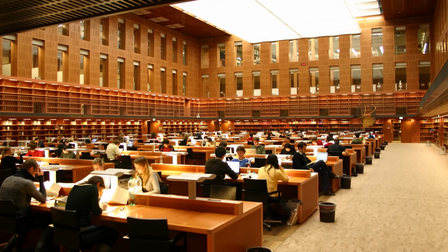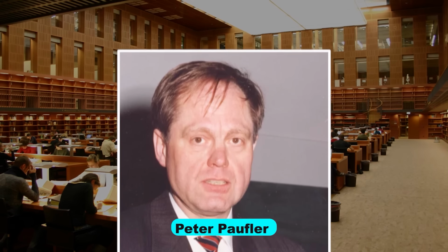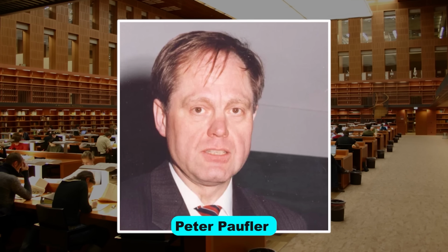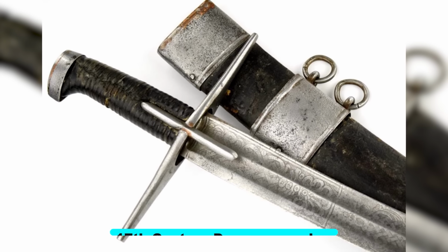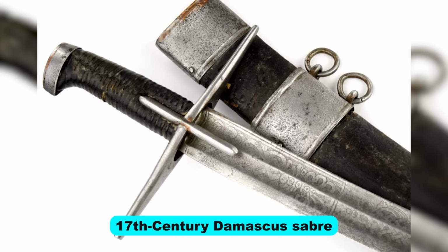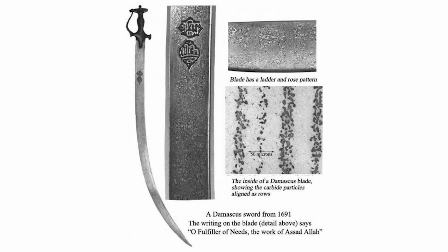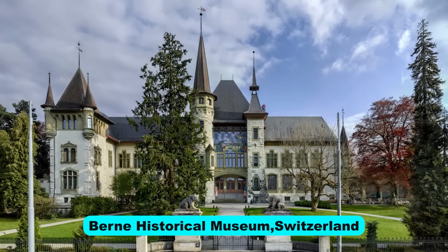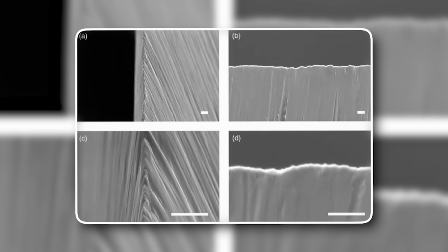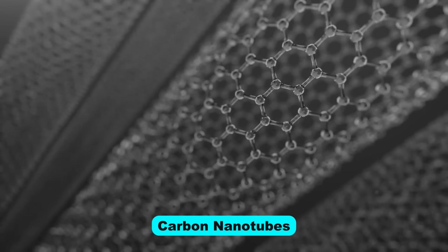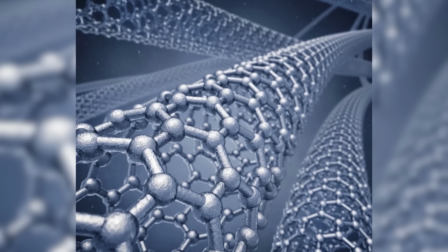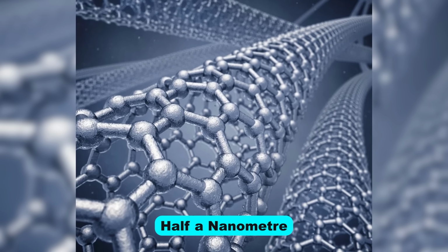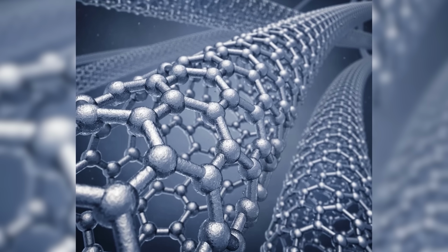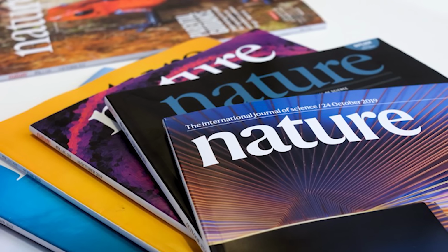In 2006, a research team led by Marianne Reibold and Peter Paufler at the Technische Universität Dresden in Germany got their hands on a section of a 17th century Damascus sabre. The blade had been made by the famous smith Assad Allah, and it was donated by the Bern Historical Museum in Switzerland. They dissolved a piece of the blade and examined it under a transmission electron microscope. Inside the steel, they found carbon nanotubes, cylinders of single-atom-thick carbon with a diameter of roughly half a nanometer, enclosing nanowires of cementite. Their findings were published in Nature.